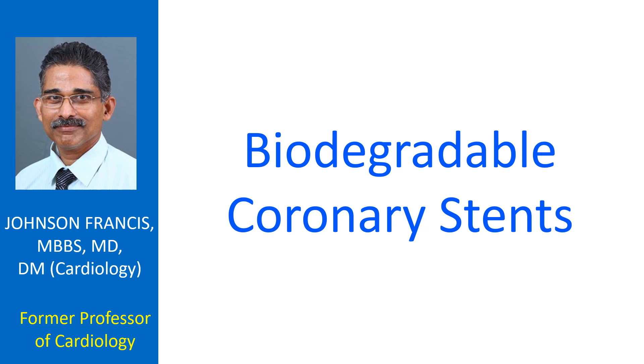To circumvent these problems, stents with bioresorbable scaffolds were evaluated. The scaffolding of biodegradable coronary stents gets bioabsorbed after a variable period of time, so that what remains is only the native vessel with good endothelial function and natural vessel curves. Polylactic acid was one of the materials evaluated for bioabsorbable stents, and it was shown to hold up to 1000 mmHg of crush pressure, being completely degraded by about 9 months.